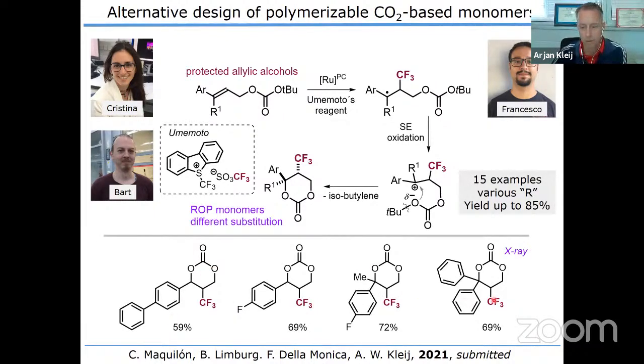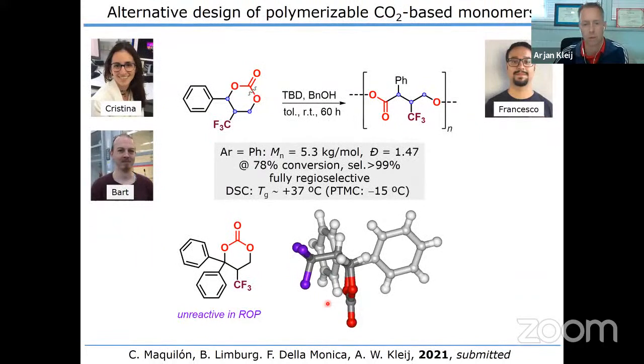So we made a number of these derivatives, so these are just a number of examples, as you see over here. And of course, we were interested in their suitability to serve as monomers for ring opening polymerization. And that is what you see over here. So what we do, we break this bond, essentially. Benzyl alcohol is here an initiator, so it's activated in the presence of a catalyst. And then we form a polycarbonate, which now has in the main chain at these blue colored carbon centers substituents. And what we do see, these are a little bit the data that we collected so far, is that the reaction is fully regioselective. So we only see one type of polycarbonate being formed at room temperature.